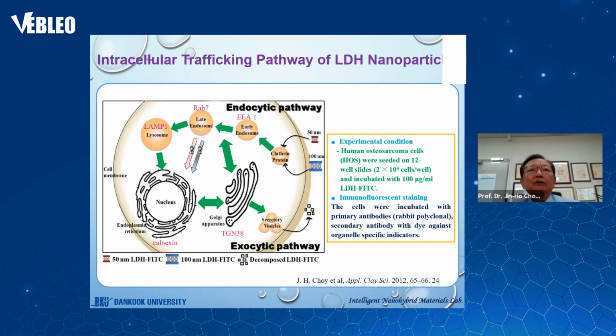For quantification of co-localization between the nanoparticles and the individual antibodies, images were analyzed from different areas of the plate, and a percentage of co-localization was then calculated from the amount of the co-localized area between total green area and red area using the curve option.